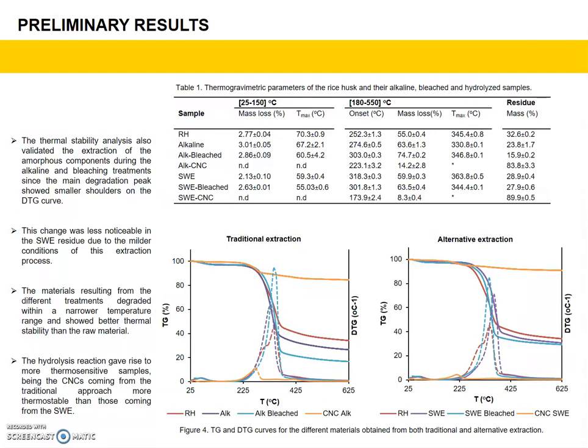The thermal stability analysis also validated the extraction of the amorphous component during the alkaline and bleaching treatments, since the main degradation peaks show smaller shoulders on the DTG curves. This change was less noticeable in the subcritical water extraction residue due to the milder condition of this extraction process. The materials resulting from the different treatments degrade within a narrower temperature range and show better thermal stability than the raw material. The hydrolysis reaction gave rise to more thermosensitive samples, the CNC coming from the traditional approach being more thermostable than those coming from the subcritical water extraction.